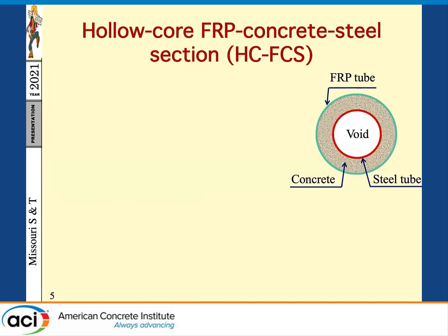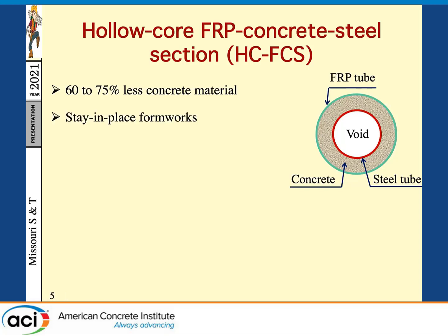So what we did over the last few years is to use a hollow core column that consists of an inner steel pipe, a concrete shell, and then an FRP tube. So what are the advantages of this hybrid system? First of all, we cut the concrete from the middle. For example, a typical bridge column diameter here in the Midwest is probably 5-6 feet, so about 2-meter diameter columns. We're talking about a concrete wall thickness of less than 5 inches, so probably 4 to 5 inches. That's about 10 centimeters or 100 millimeters. So we significantly reduce the weight, about 75% less concrete material. You can link this also to using less material, so it's more sustainable.